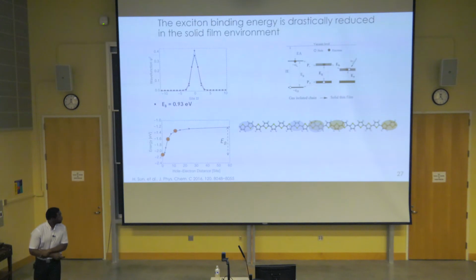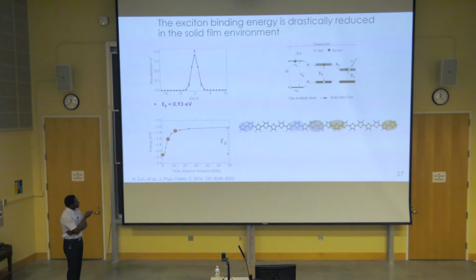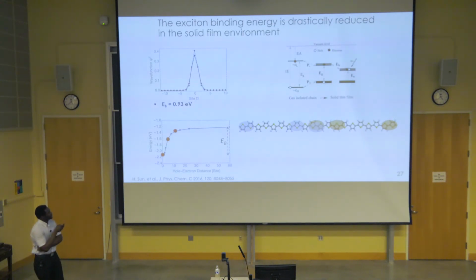And so the exciton binding energy will be the difference between the optimal exciton, where we have zero separation between the charge carriers, and the completely separated carriers stabilized by the medium. So what happens is the polarization effect, or the stabilization of the medium, has led to a reduction of the binding energy of the exciton.